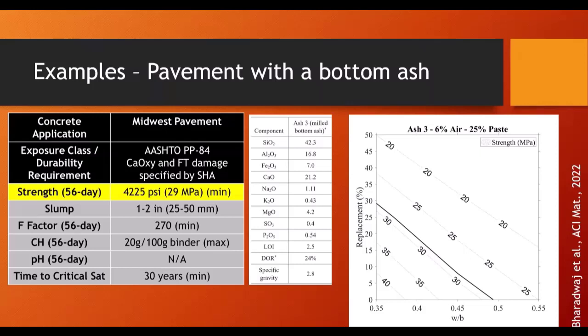Calcium hydroxide content, so we don't get into a problem with the icing salts, pH, so we don't have a problem with ASR, and then freeze-thaw resistance. And if you tell us all these things up front, we can actually simulate and come up with a graph like you see over on the right-hand side, which is the strength as a function of the water to binder ratio versus the SCM replacement on the y-axis. Everything that's above that solid line that's around 29, those are all mixed designs that will not give you the performance you want. Anything that's below that line and down into that corner, those are all feasible solutions.